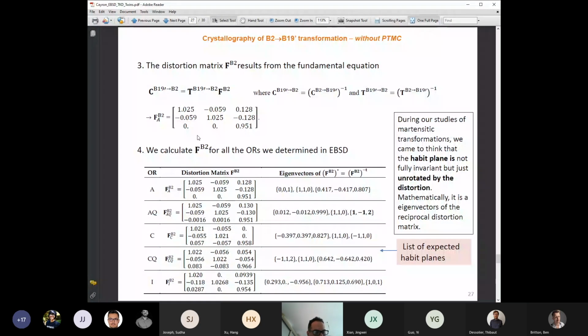And if I want to predict the habit plane, the plane between martensite and austenite, it should be unrotated by this distortion matrix. So it should be an eigenvector of this matrix taken in the reciprocal space. And here in bold, I don't know if you can see, there is a 1, -1, 2. So it is one habit plane predicted by the calculation.